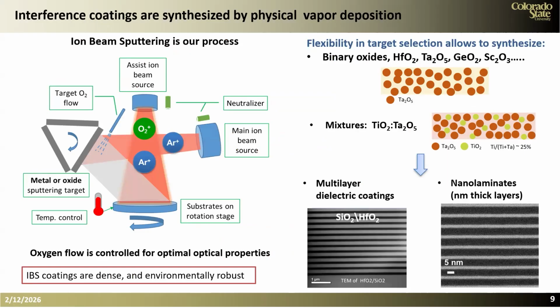We grow our films using a technique that is called ion beam sputtering. And I show here a schematic of the ion beam sputtering system that we have downstairs here at the ERC, and that some of you are using. So in this system, we have a main ion source. This ion source produces a beam of ions, typically argon ions, that sputter a metal target, and they dislodge atoms and molecules from the target, producing a plume that then deposits onto the substrate. And the substrate is typically rotating for uniformity purposes. We do all of this in an oxygen-rich atmosphere because we want to make oxides. And we control the temperature of the substrate.